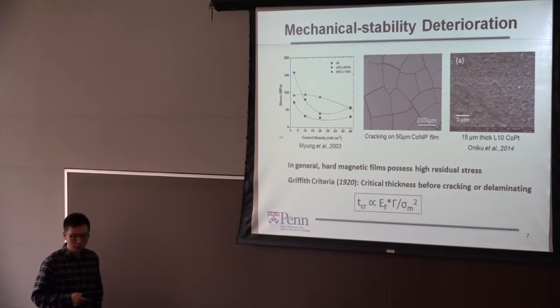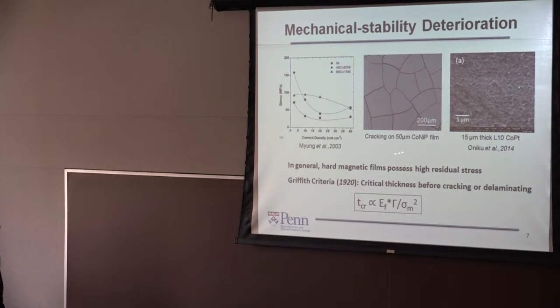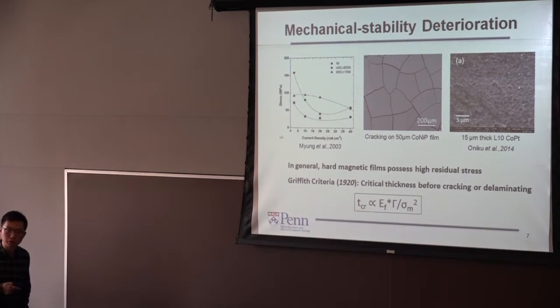The other problem is the mechanical stability. In general, these hard magnetic films possess very high residual stress. And as you know, when the film thickness increases, the stored strain energy inside the film also increases. And according to Griffith's criterion in fracture mechanics, when the energy release rate is higher than the fracture toughness, the film will have spontaneous cracking or delamination. What that really means is there is a critical film thickness for a film with a certain residual stress, beyond which the cracking will happen. And this critical thickness is proportional to 1 over the stress squared.